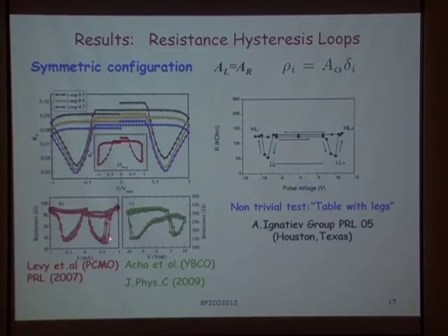And this is a result from experiments performed by Carlos Acha, here also at Buenos Aires, at the Laboratorio de Bajas Temperaturas at the University of Buenos Aires, on a sample based on YBCO. This is rather different from this one. I'm going to explain a little bit later why this behavior can emerge in comparison with this one. But here, one of the first results is that our model simulation can reproduce quite accurately experimental results.